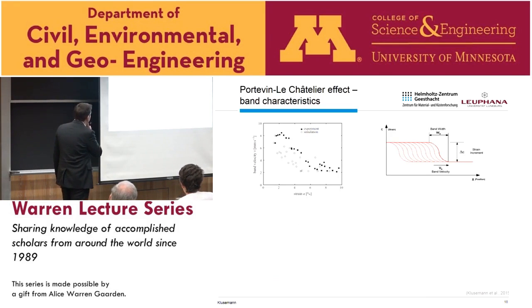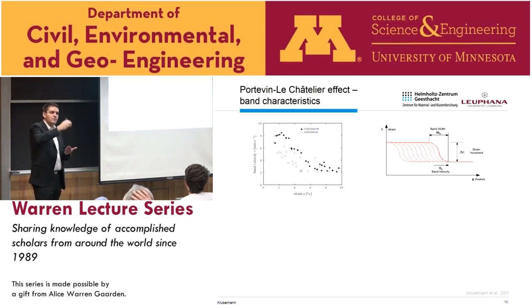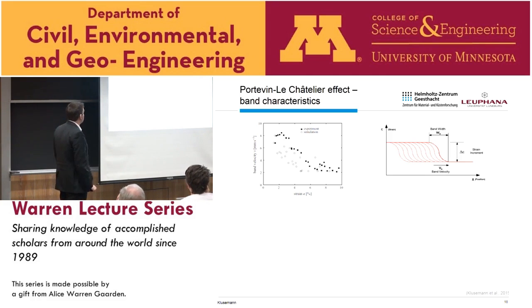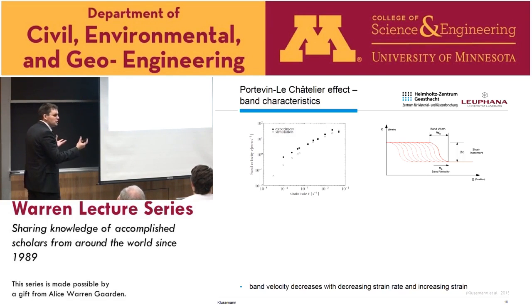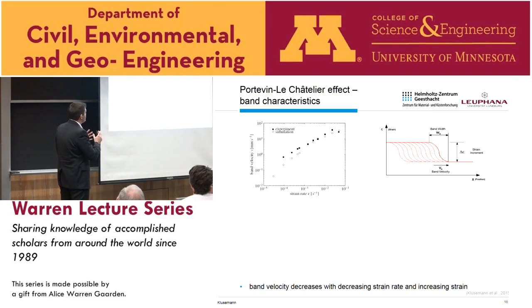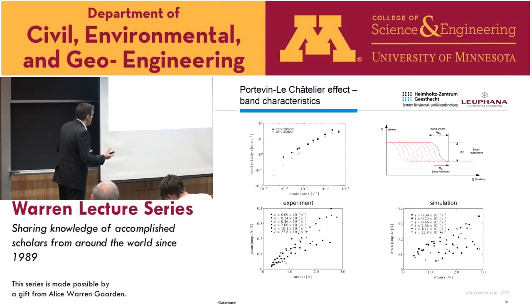Then we quantified this a bit in terms of band characteristics. First, we investigated the band velocity, and what we saw in particular in the experiment, a bit stronger, was a decreasing velocity with increasing strain, also for each of the PLC bands. But at the beginning we had a short increase, just from 0.2% until 1% strain, of the band velocity, and then it always decreases. When we take the average of the first, I think it was 10 PLC bands, we saw the tendency that the band velocity increases with strain rate, or of course decreases with decreasing strain rate.